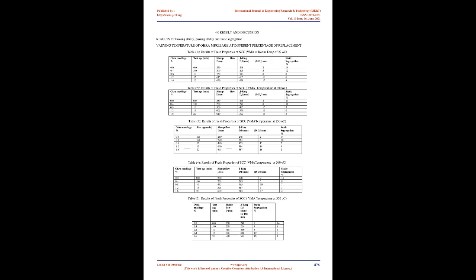The test was completed after the concrete flow had ceased. Note: do not touch the base plate or otherwise disturb the concrete until the measurement described below was completed. The largest diameter of the flow spread, d_max, and the one perpendicular to it, d_perp, were measured using the ruler.